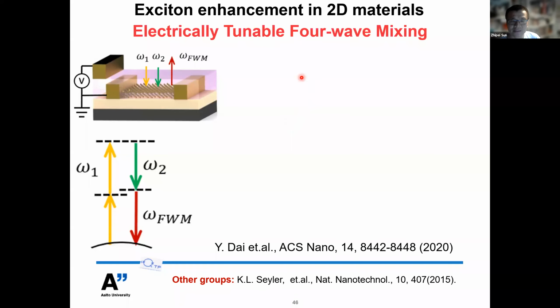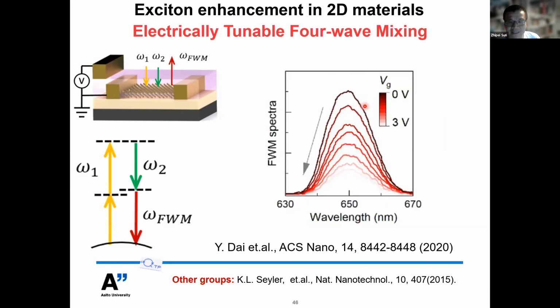So here we take this excitonic enhancement, and we demonstrate electrically tunable four-wave mixing inside MoS2 with this exciton resonance. This is our typical MoS2 transistor structure. We have input light at λ1 and input light at λ2. Then we look at the wavelengths generated by this four-wave mixing process. This is the result. You can see here the four-wave mixing response can be fully tuned by the electrical gating. The reason is that when we increase the gate voltage, the doping of the flake will change the oscillator strength of the exciton. Therefore, we can tune the nonlinear optical response inside the MoS2.